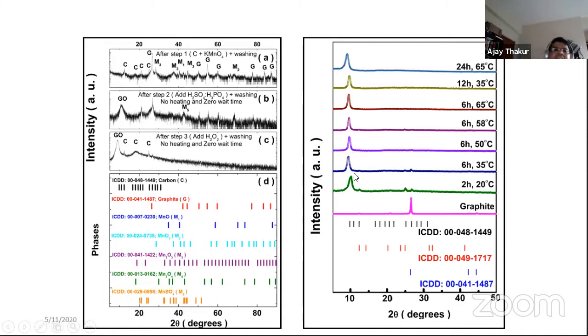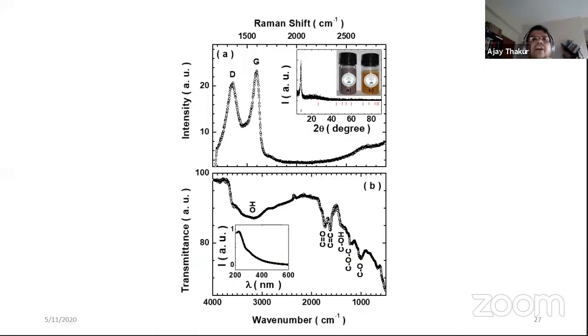So only the graphene oxide peak was observed. XRD was really exhaustively used in our experiments to ensure that we are reaching the right phase and right conditions for preparation of this. This was followed by doing FTIR for looking at the functional groups which are attached to the sp2 carbon backbone. We found that groups like C=O, C-C, C-OH, C-O-C, and C-O single bond were predominantly the functional groups, and also the OH group.